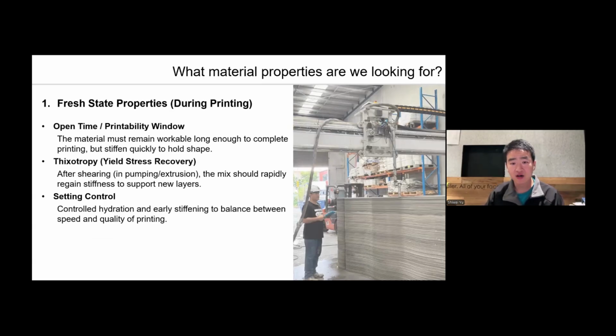And the next one is the open time, which is also the printability window. The material needs to stay workable long enough for us to complete the printing, but then stiffen quickly so the structure can hold its shape. In practice, the time the material spends in the hose can range from 1 minute to 10 minutes. That's why open time has to be carefully adjusted for different projects. If you use a fast-setting mix in a long hose, you can easily end up with a blockage.